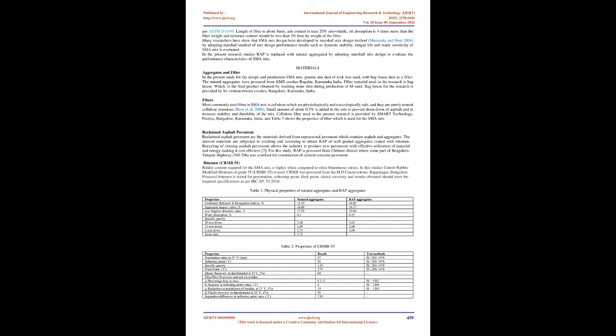Stone-on-stone contact formed in the mix makes it more rut resistant and a highly durable mixture. Stabilizer additive: fibers are added because, due to high binder content, drain down of bitumen from SMA mix occurs during production, transport, and laying of the mix. Hence, in order to prevent the drain down, fibers are added, which may be organic, inorganic or mineral materials. Fibers such as coconut coir, glass, minerals, and cellulose fibers, only pelletized, can be utilized.